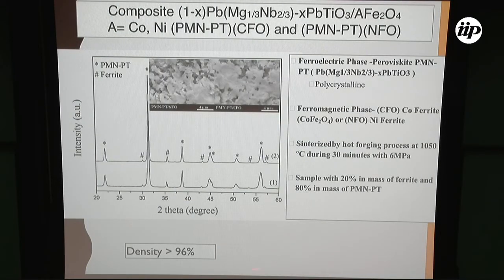The study in our group is based on these composites: PMN-PT with cobalt ferrite, and PMN-PT with nickel ferrite. This material is a polycrystalline composite, and the grains are either cobalt ferrite or nickel ferrite. The samples studied are 20% ferrite and 80% PMN-PT in mass, with a good density of around 96%, which guarantees the possibility of polarizing the sample. If you don't have a good density, the sample cannot be polarized well.